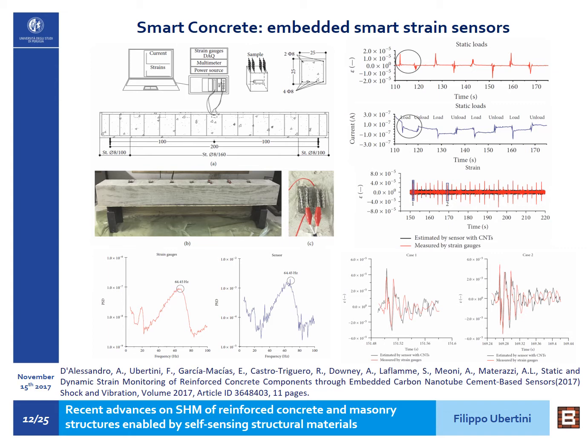Also noticeable is that if we take the power spectral density of the signal acquired by the strain gauge and by the smart concrete sensor, the power spectral density have a leading peak that is exactly at the same frequency of about 64 Hz, which allows to conclude that these smart concrete sensors are suitable to be used as vibration sensors, at least for modal frequency identification in reinforced concrete structures.